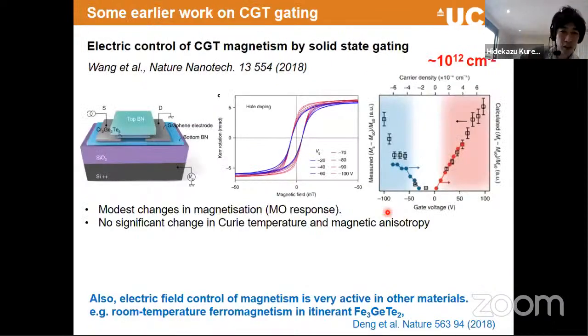Right, so just a quick mention of the previous work. A similar study has been done by Wang et al., where they use silicon oxide as a solid state gating capacitor with a back gate, and they try to measure the magnetic property by the magneto-optical effect. So this is the Kerr rotation signal as a function of magnetic field applied out of plane. What they observed is a very, very subtle change of the Kerr rotation angle, which should be proportional to the magnetization. They didn't see anything in the change of the Curie temperature or in the change of the magnetic anisotropy.